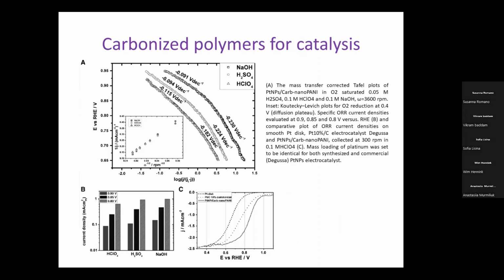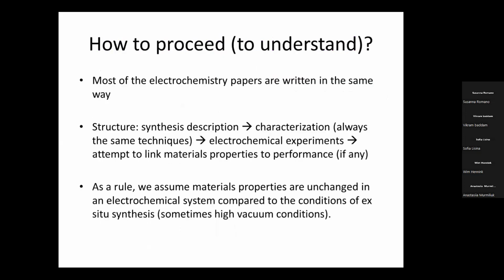What's interesting is we actually found it more active than the commercial platinum carbon catalyst, which we don't fully understand. We believe that there are some very important effects of the morphology for diffusion and so on, and also the role of heteroatoms in the surface. But there is also a question of how to proceed further.